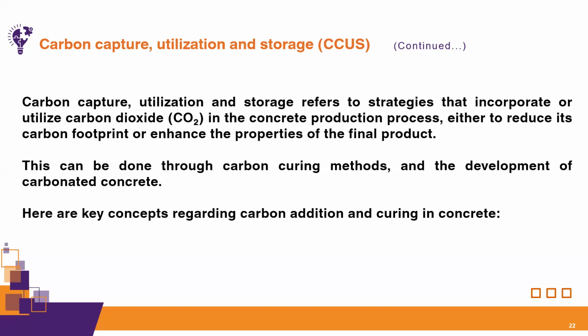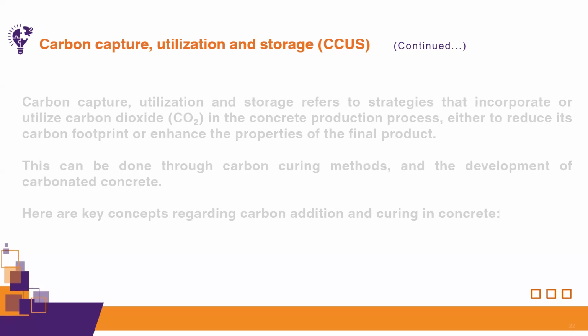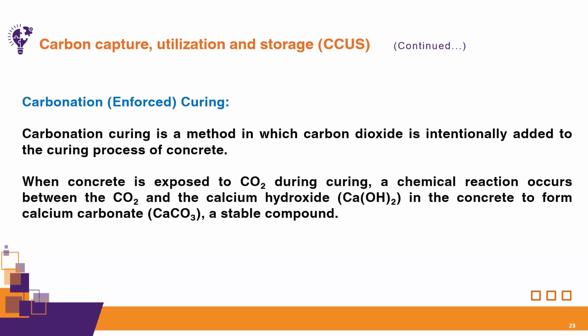The key concepts regarding carbon addition and curing in concrete are discussed in this slide. First of all, we can use carbon for curing purposes. The carbon which is emitted from the cement plant or any industry, we can capture and then utilize for curing. So instead of water curing, if we cure our concrete in a carbon environment, this is basically called carbonation curing, and it is also called enforced curing. Carbonation curing is a method in which carbon dioxide is intentionally added to the curing process of the concrete. So we will cure our concrete in a carbon environment.